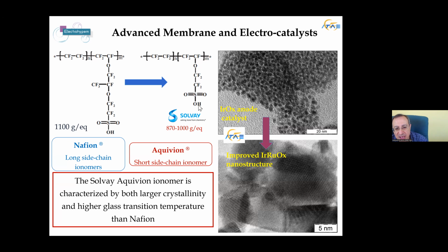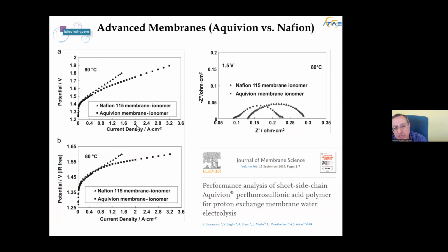So we have electrons going through this side chain, meaning better separation between oxygen and protons. Oxygen remains anchored and protons move, giving better dissociation. Aquivion also has high glass transition temperature and good crystallinity, so it is more robust than Nafion. This was shown in several papers published together with Solvay, showing lower series resistance, better conductivity, and better interface with the electrodes.